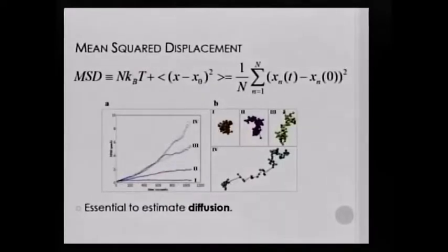The mean square displacement basically allows us to estimate how much a given particle of the system travels. We can see here, for example, a sampling of an atom, and you can see that it can occupy different positions over the system. So this is an essential property when you want to estimate, for example, self-diffusion, or diffusion of one species into another. It's a very important property. I believe maybe Tonão is going to talk a little more about this in his talk.